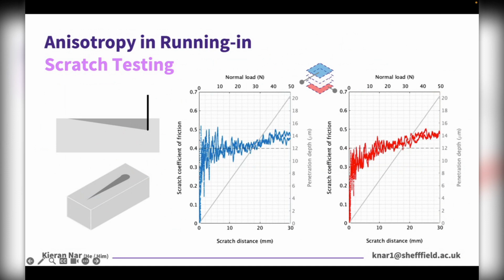So, similarly to before, we can see that during initial sliding, top surfaces experience these heightened friction responses relative to bottom surfaces. As the test progressed, we saw that these scratch coefficient of friction responses became more and more similar. This indicates that, from a friction perspective, the transition from transient to steady state sliding occurs when the penetration depth of the indenter also transitions from surface to subsurface ploughing.